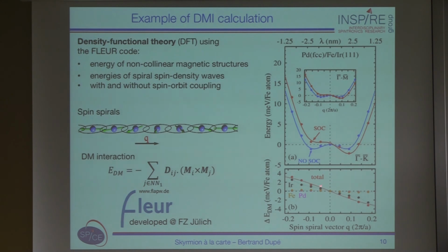And so here you see that the iron and the palladium, which are 3d and 4d metals, have actually a negligible contribution. Their contribution is mainly zero. You see that here is the black curve. The black curve is the contribution of the iridium. The iridium is a 5d element, so you expect that a 5d element has a large spin-orbit coupling, and indeed, it's the main contribution to the total spin-orbit coupling here.